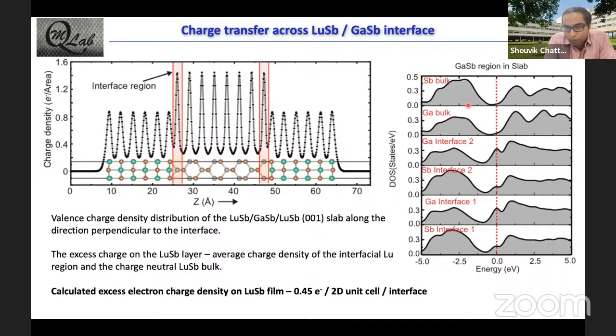What we're plotting is this density of states when you're deep inside the bulk. There is not much contribution from the interfacial states. But when you come closer to the interface, you have a very large contribution from your interfacial states.